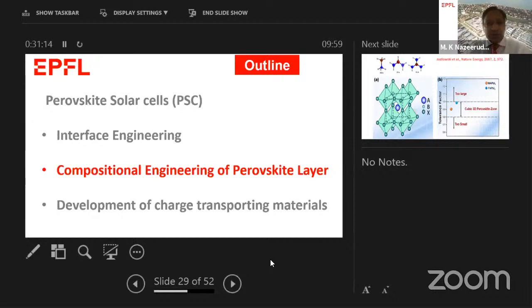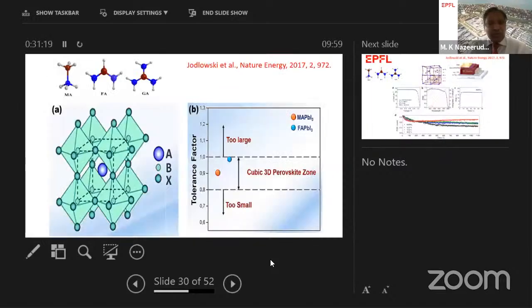So let's say, next slide, please. So here, what we are doing is, on the top, I'm showing you the three cations: methylammonium, formamidinium cation, then we have a guanidinium cation. So methylammonium and formamidinium form three-dimensional perovskites, and when we have these cations, the tolerance factor comes within 0.8 to 1. So within this tolerance factor, the perovskite layers usually form cubic, this is a cubic zone.